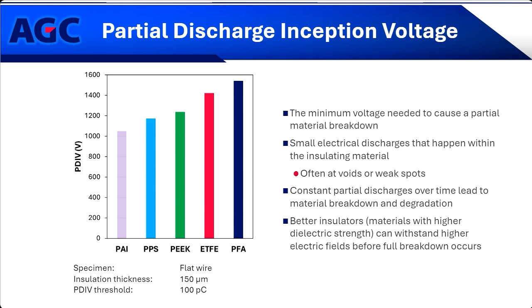So not surprisingly, the PFA and the ETFE, the materials that have the lowest dielectric constant, were our best performers in this situation. And if I were to go back to the previous slide, which I will not, but if I were, you would see that we follow the exact opposite trend. As I mentioned, they're inversely proportional, typically. Again, not in a linear fashion, but the inverse of the behavior of your dielectric constant will give you your partial discharge inception voltage behavior.